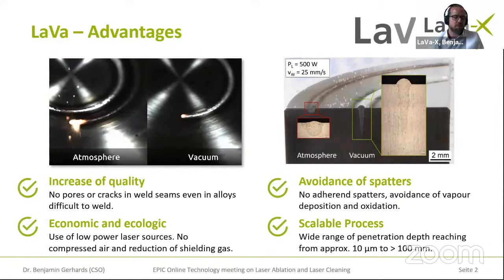And the other is that we need a very, very good bevel preparation in terms of pollution. So we do not want any greases or any oils or any organic materials inside of our bevel preparation, because those materials expand when the laser beam goes over them. And this leads to a large amount of spatters and in the worst case of weld pool ejections.